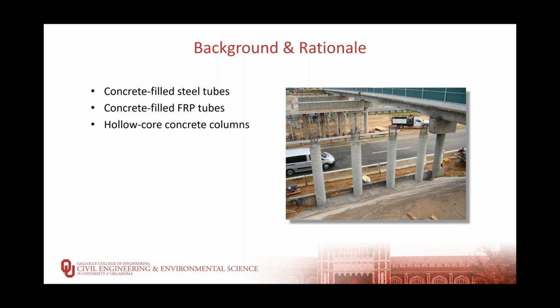Other researchers have examined hollow core concrete columns, the idea being to reduce the weight of the columns and use them as precast elements shipped out to the job site. So the hollow core would eliminate a lot of the concrete in the center that didn't add to the strength and durability of the system and make it lighter for shipping it to the job and erecting it in place. There still had to be splices made, either reinforced concrete splices or potentially post-tensioning the segments together, but it was an additional benefit in terms of reducing the weight and increasing the speed of construction.